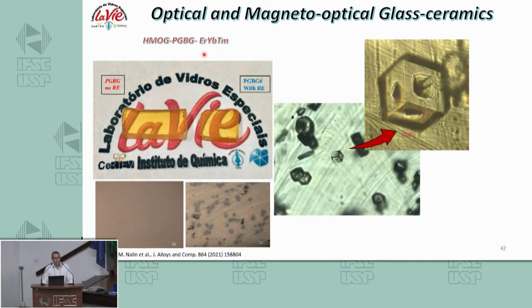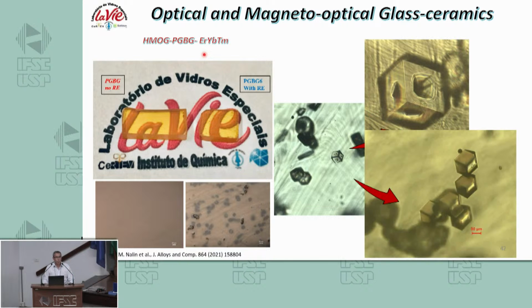supersaturated method that I told before. Okay? So depending on the amount of rare earths that you put inside, the glass is quite stable. The Tx minus Tg, that was the parameter that we use for the stability of the glass, is around 250 degrees. So we can easily use this glass to prepare optical fibers. But when you put 1 or 2% of rare earths, it's completely destabilized. There is a formation of a crystal. But okay, it's quite nice.